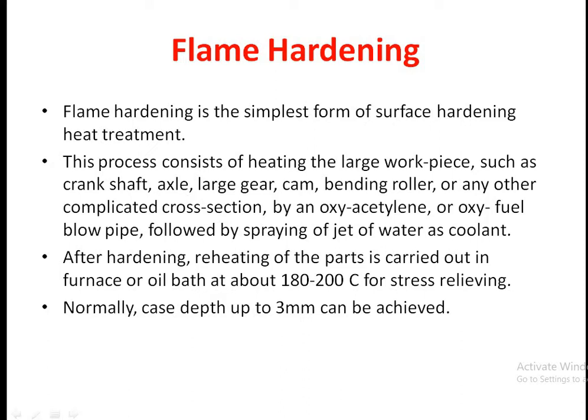Whenever a part is suddenly transformed from one phase to another, stresses are induced which can have undesirable effects. To remove these stresses, the part must be reheated in a furnace or oil bath at the specified temperature. The case depth achievable by flame hardening is up to 3 millimeters.